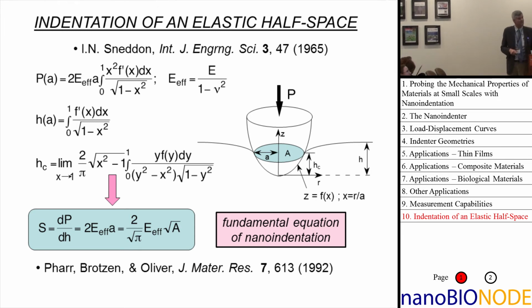Now that's a big mess, but one of the things that we showed early on is that all this mess up here can be simplified to a very simple relationship that looks like this. This says simply that the stiffness of the material in contact, which is the slope of the force-displacement relationship. So we're measuring forces and we're measuring displacements. We can measure that slope with a lot of accuracy, that's equal to 2 times the effective modulus, the effective modulus. The effective modulus is a combination of the modulus of the material and the modulus of the indenter,